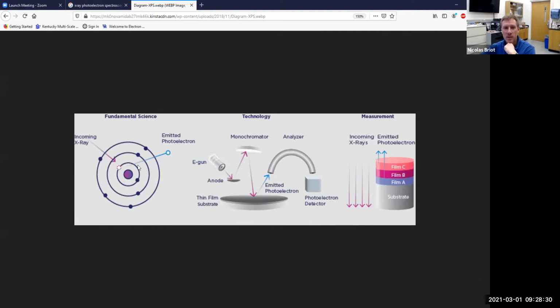So the way it works, again, that's the physics of it. The instrument is looking like this, just like an XRD, X-ray diffraction system. X-rays are made by shooting electrons at an anode, a material, and then those are the X-rays that we focus and send to the sample. If you start seeing this, that really also puts in perspective what we do when we do EDS. When we do EDS, we do this part. Instead of using an anode, like in XPS or XRD, where you have a really pure copper or aluminum plate, in EDS that would be your sample here, and you get all of the X-rays. In XPS or XRD, you have a pure material, copper or aluminum, and you try to select only one very fine X-ray energy and use that as your incident signal to analyze your sample. So anyway, we shoot the X-rays to the sample, get the photoelectrons, they go through an analyzer, and then you can detect what's coming out of it.